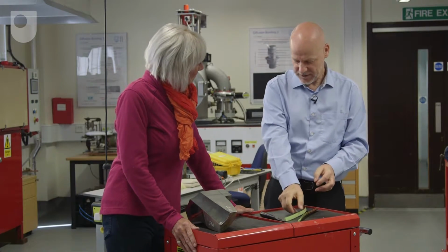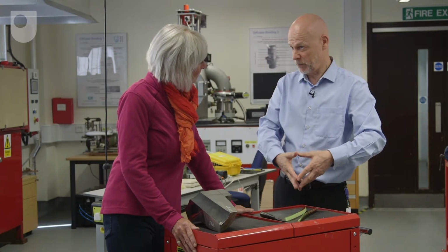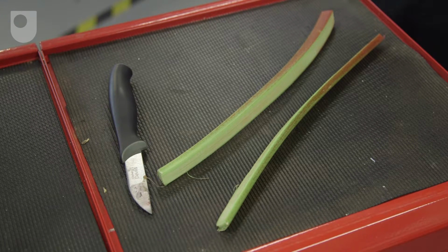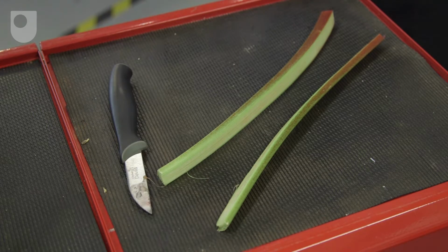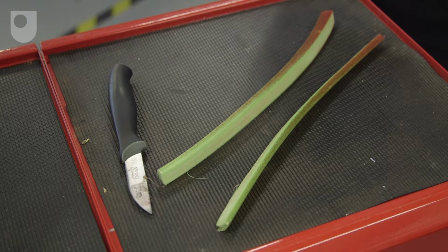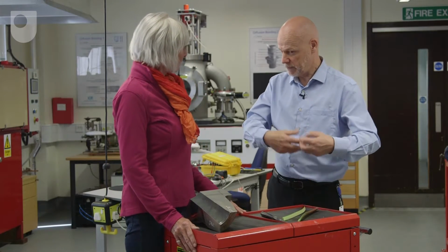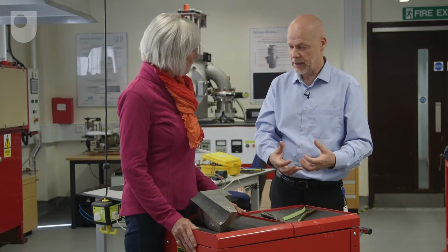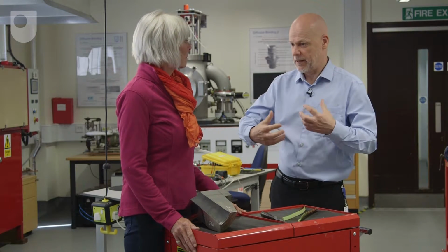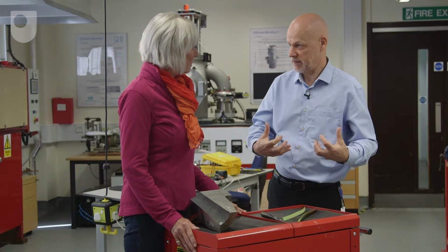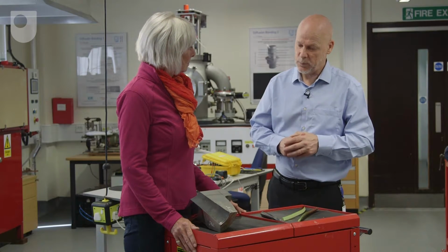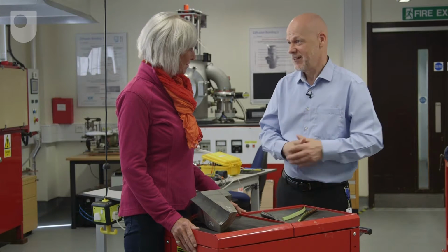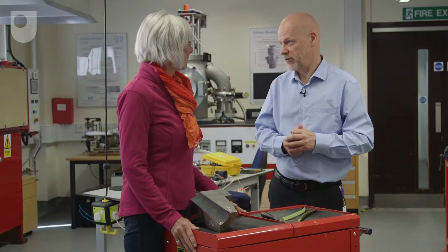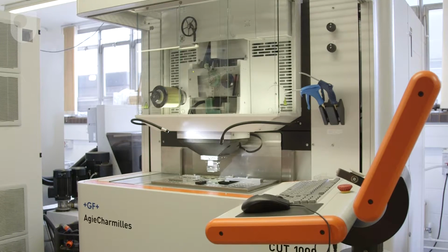Well, this actually illustrates the principle that if you cut a component with residual stress inside into two parts, the cut faces deform. Right. So we've adapted this technique, or at least we implement this type of cutting technique on metallic components to find out if there's any stress inside. And we cut metal not by a knife, but using a technique called electro-discharge machining. Now this technique involves a very fine wire, which may be about 1/4 millimeter diameter.